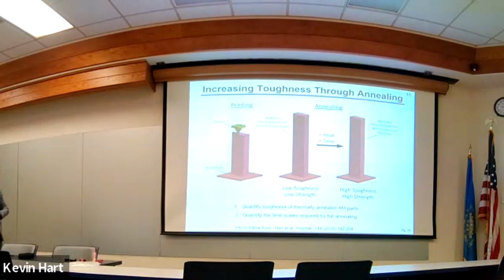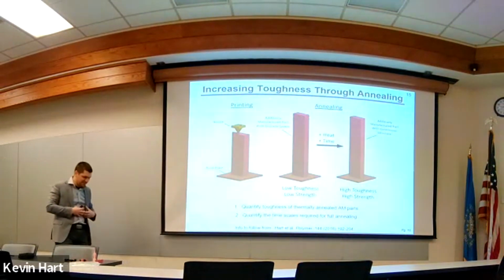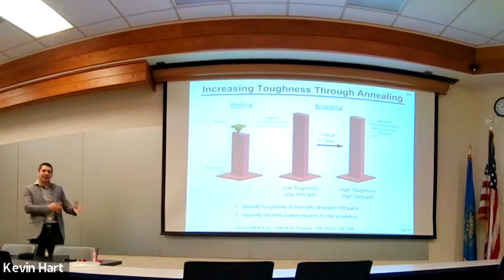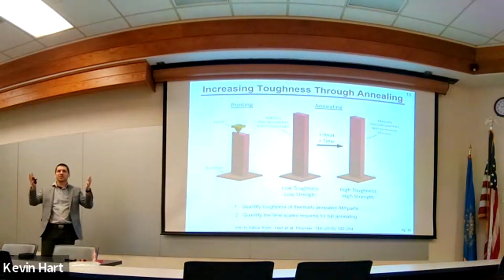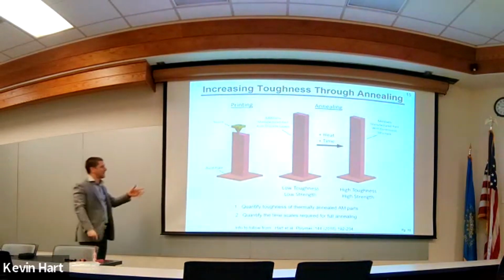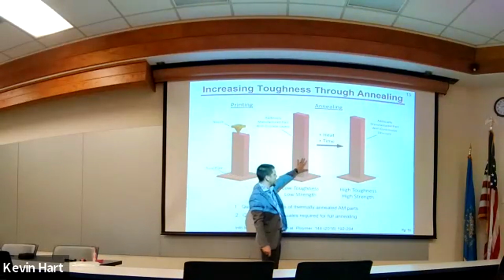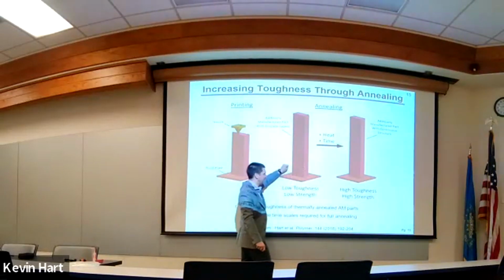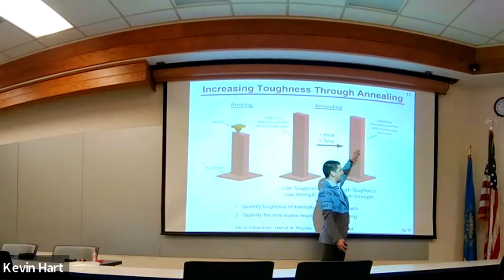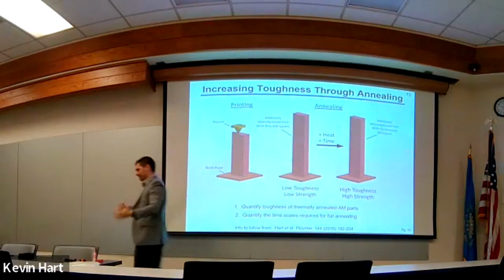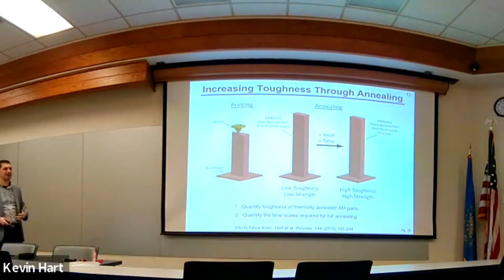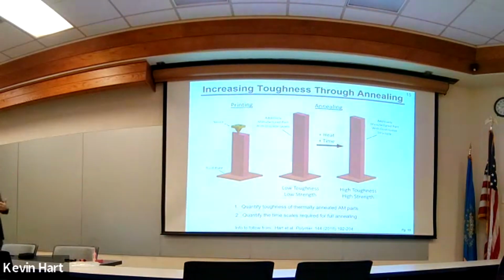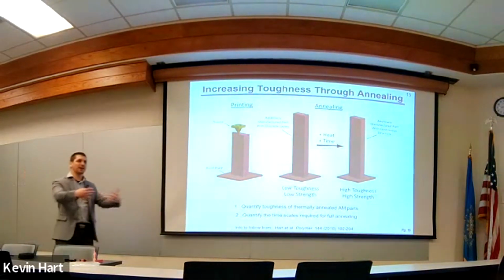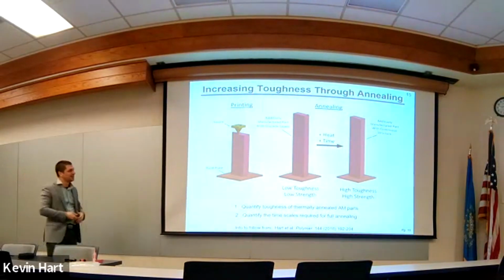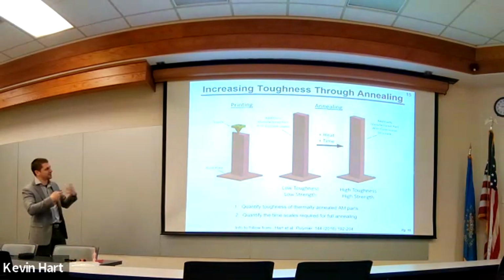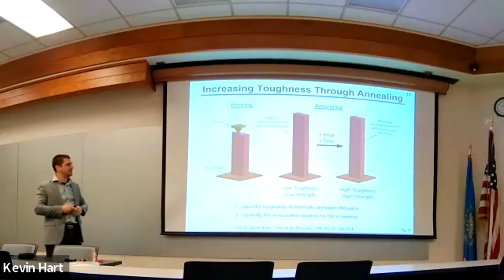So, very primitive. One of the first things that we wanted to do is understand, all right, we want to do this reptation. We want to take our 3D printed sample and get the polymer chains to move across the interface using temperature. So let's 3D print our sample. Here we are. We know that this is generally low strength and low toughness. It sucks. We never use it in an engineering application. Then we're going to apply some heat to it for some amount of time and transform it into an injection molded piece, just by basically melting it together. Very primitive, very crude, but the whole idea here is that science works in steps. We've got to figure out what time and temperatures are required, how long it takes. All the physics that go into this are important to us. So this is step number 1, figuring out what annealing is required, heat and time.